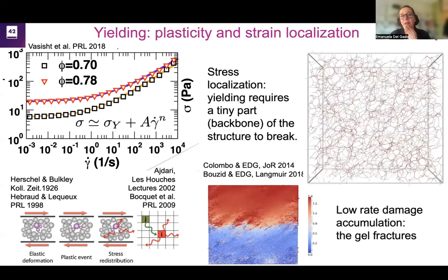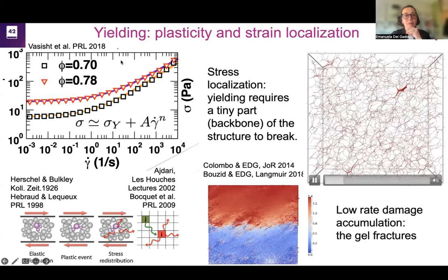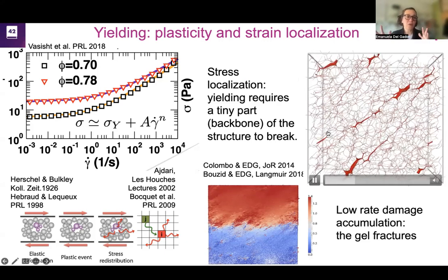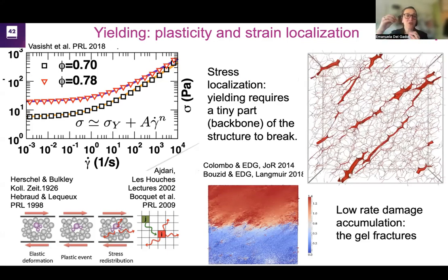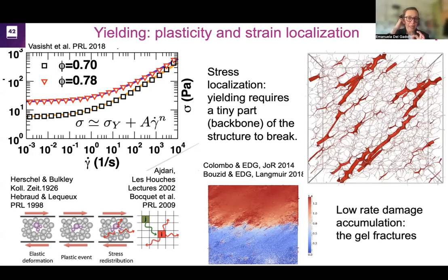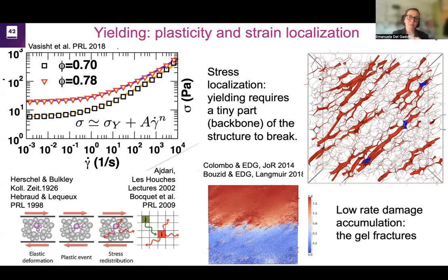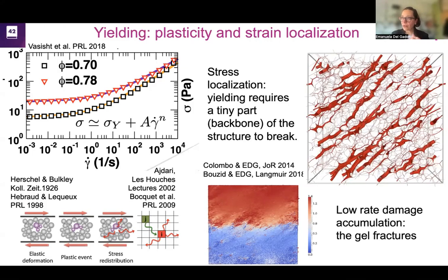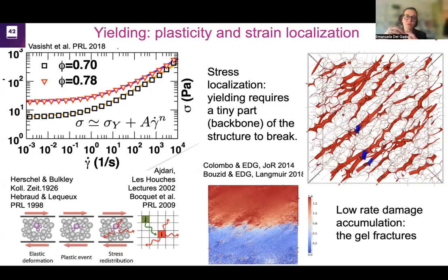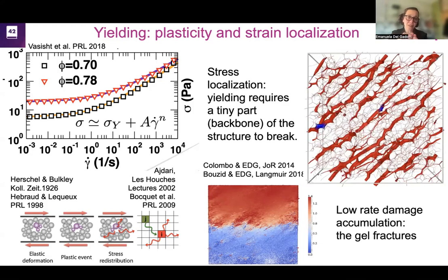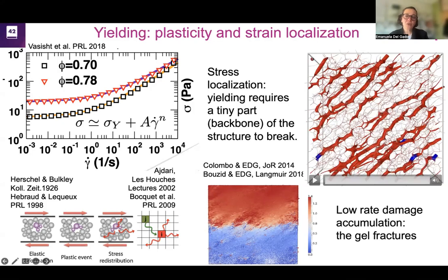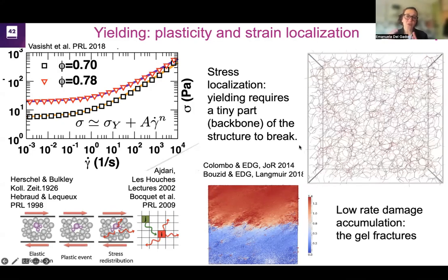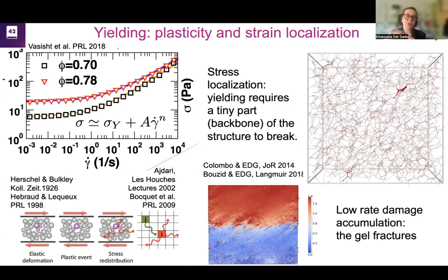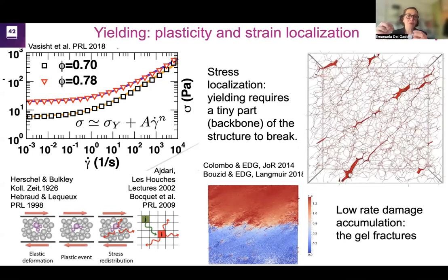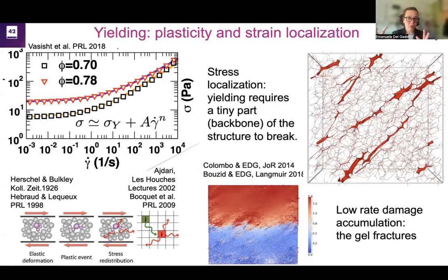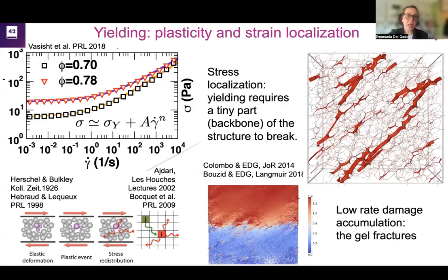So we see this even in gels. This is from our simulation. On the right, you see one of our gel models where I'm showing you just the network, the connections between the particles. In this visualization I'm also measuring the stress across the different parts of the structure, and I'm drawing as thicker the regions where there are larger tensile stresses. As the material starts to deform, the parts that become thicker are regions where the stresses are higher. So you can see how the stress is localized in a tiny part of the structure. And then things get stretched out, and when they become blue, that's when they break.